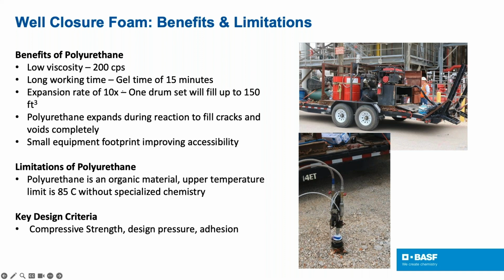There can be a trade-off in some of the properties if the formulation is modified. For example, reducing the density to allow less material will result in lower compressive strength, meaning the PU may not withstand the pressure of some of the gases being emitted. And other considerations would be, are there bends in the pipeline? Bends would increase the allowable design pressure by providing physical blockage. In addition, any chemical or mechanical bonding of the urethane to the ID of the steel pipe.